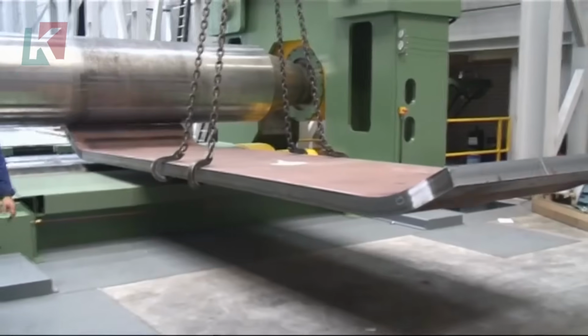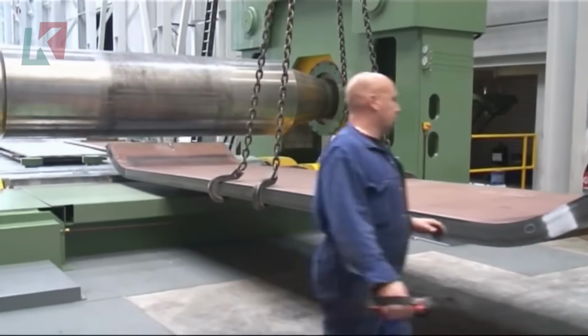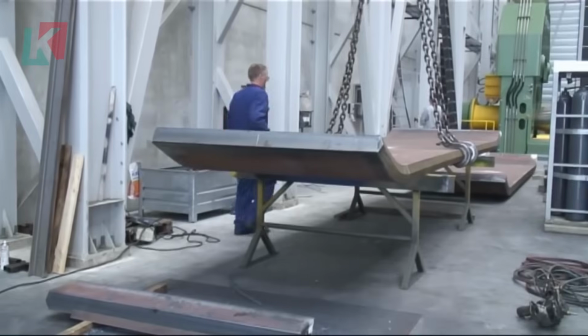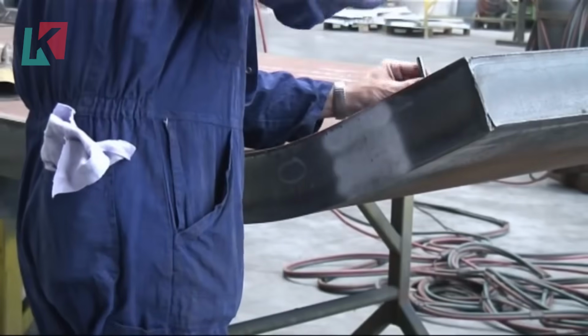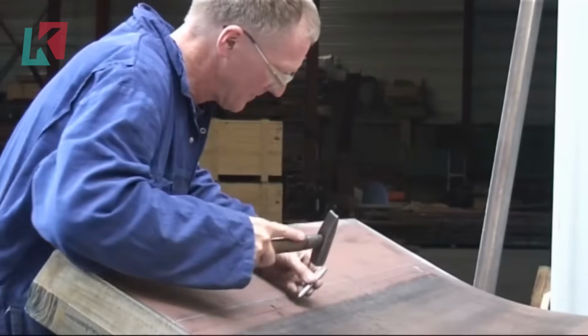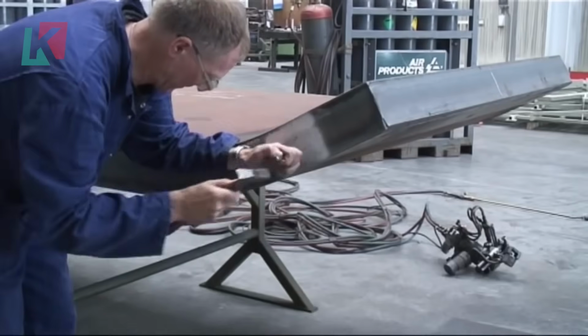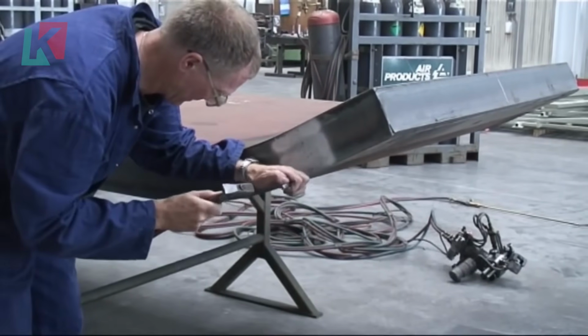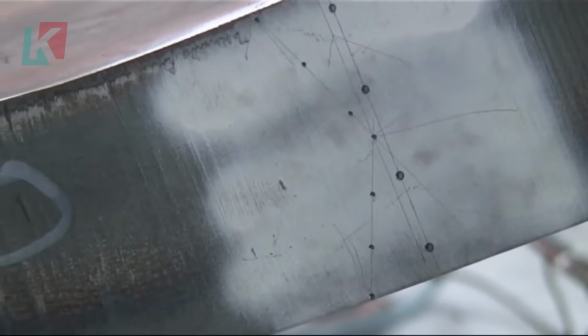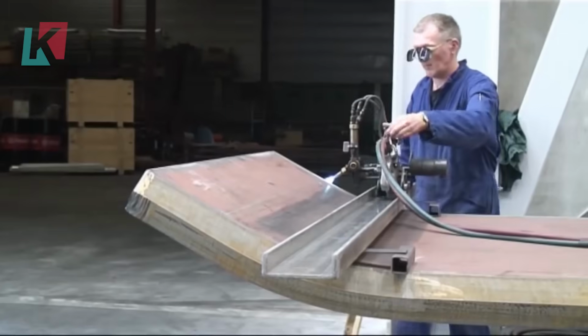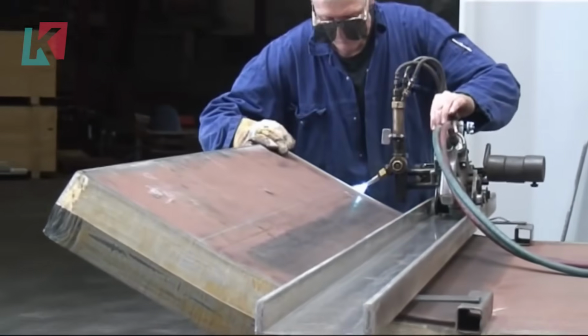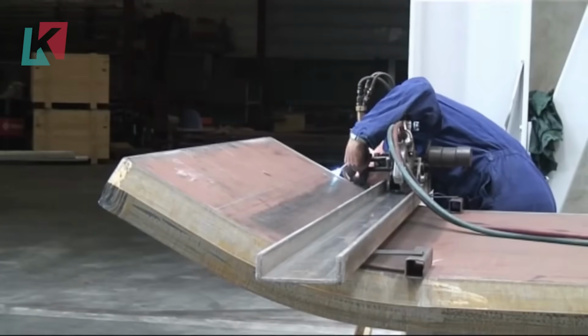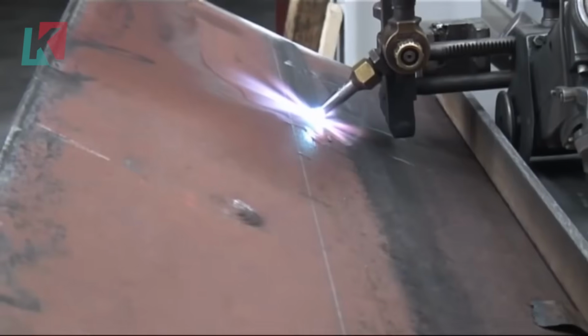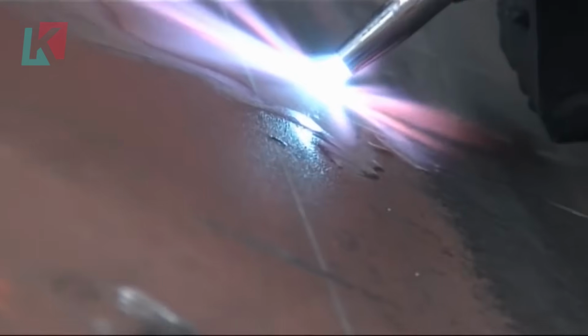But it's not just about raw power, it's about controlled power. The hydraulic cylinders can adjust pressure in increments so small they're measured in fractions of a PSI. What makes Haeusler machines special is their CNC control system. That operator isn't just guessing at settings, the computer is calculating the exact roll positions needed based on the material properties, thickness, and desired radius. The system accounts for spring back, work hardening, and even temperature variations in the steel.